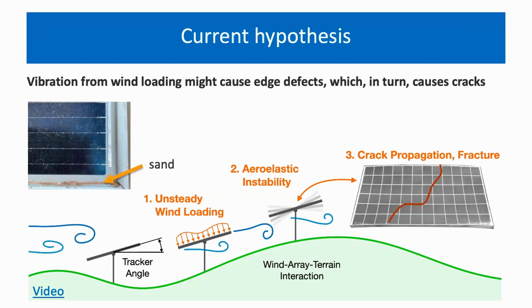So what we think is happening in the field is that there's an interaction between the aluminum frame and the glass laminate. You can see we removed the aluminum frame here, and it can happen that there's sand in there. So with wind vibrations of those mounted modules, we expect there might be some scratching on the glass surface between the aluminum frame and the glass, which then introduces scratches and voids, which might cause cracks to propagate similar to this.